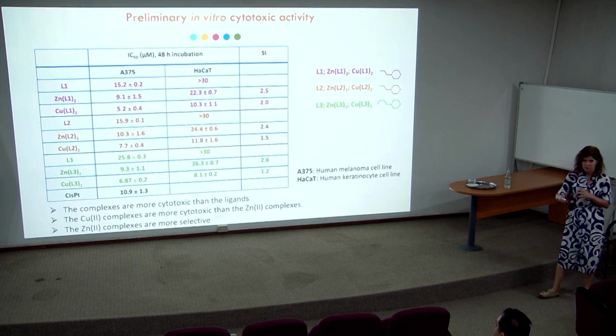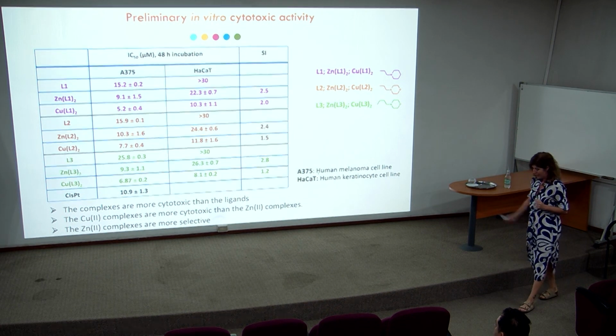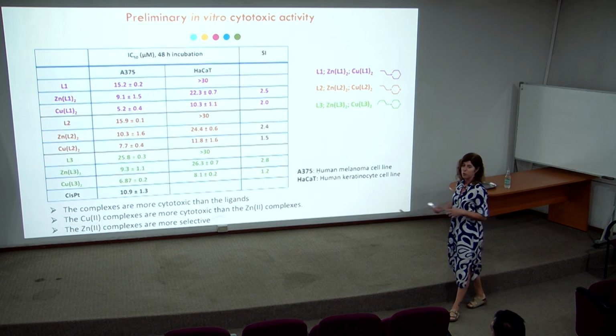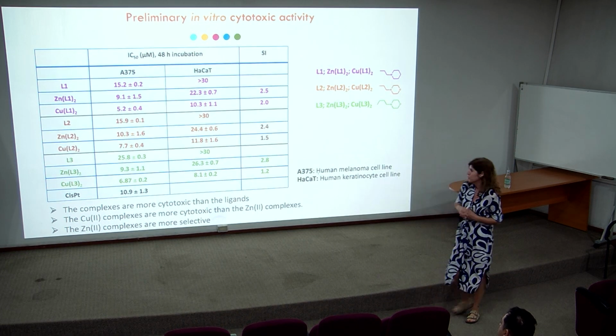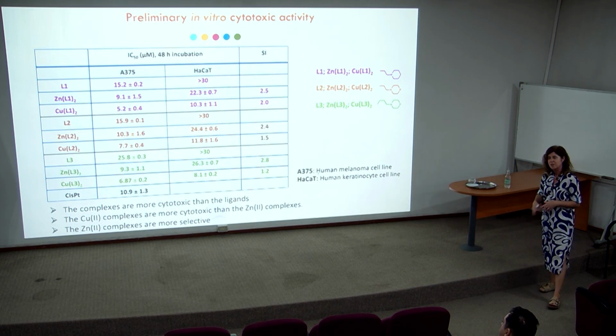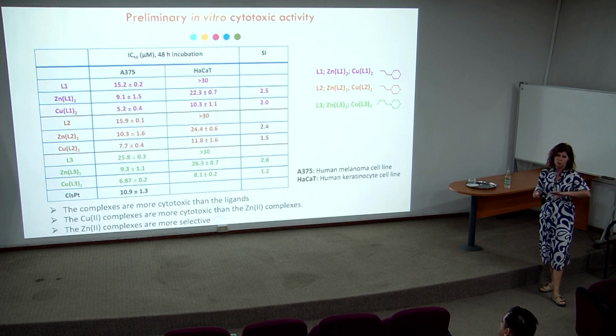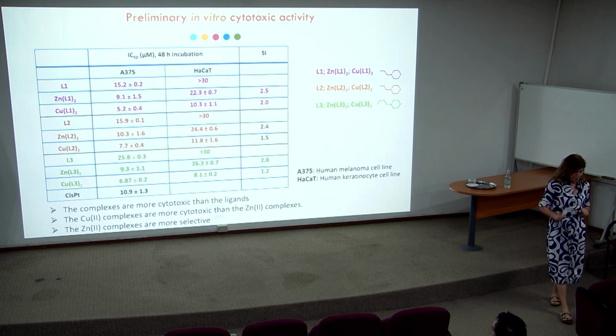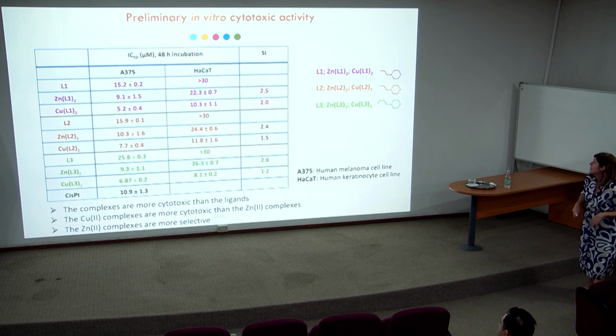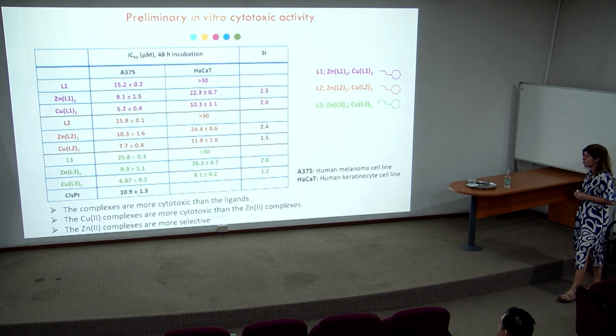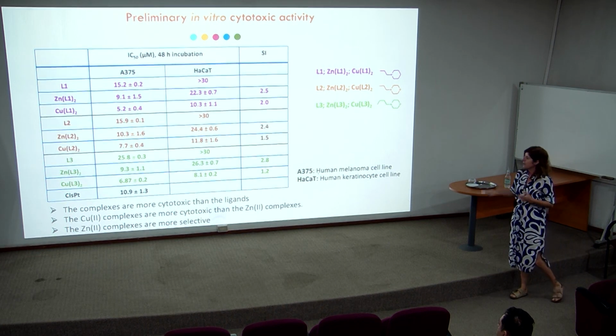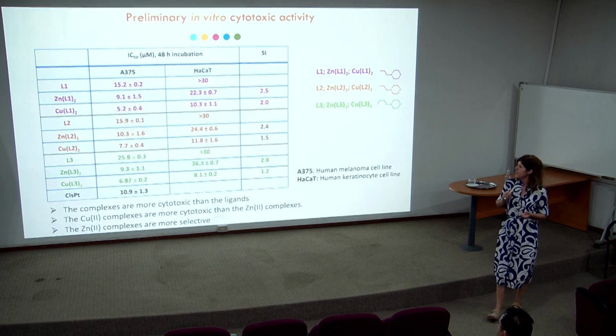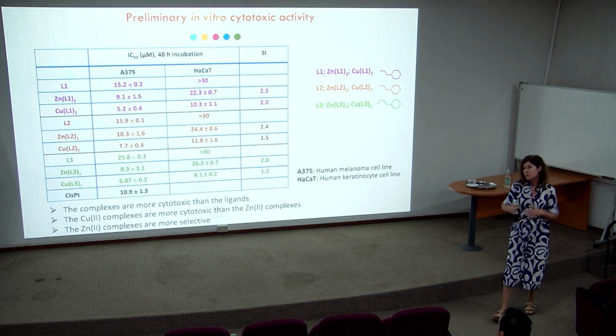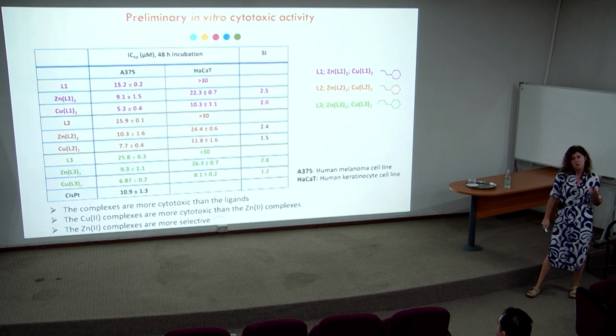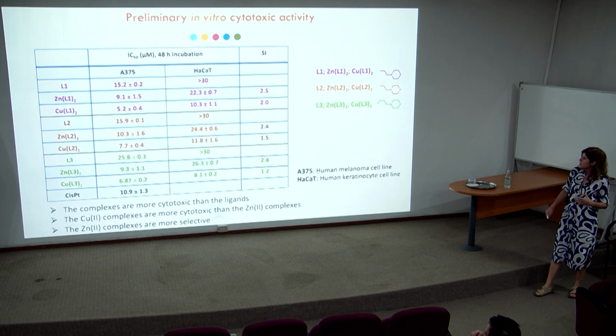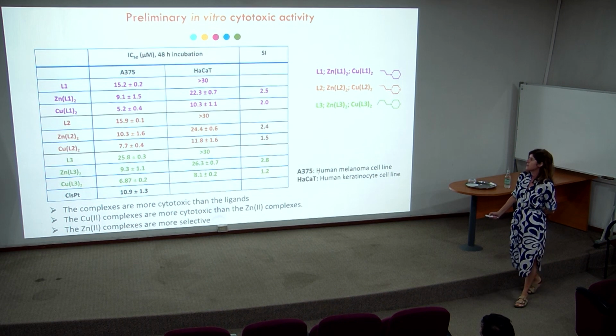We also formulated the system that I showed you before. We also tried to incorporate one of the copper complexes into the liposomes, but the incorporation efficiency was very low. So we decided to drop that compound and to proceed with this one. I don't have results to show you yet, but I hope I will have in the future. And I will say that we have also prepared with these ligands the vanadium, the nickel, and the iron compounds. So they are being tested in different types of cancer cells. And so I hope to have some interesting results from this system.